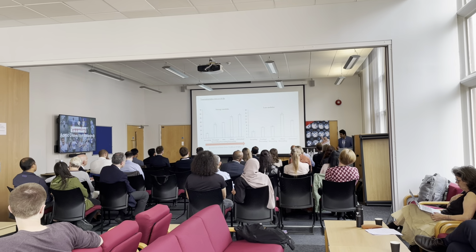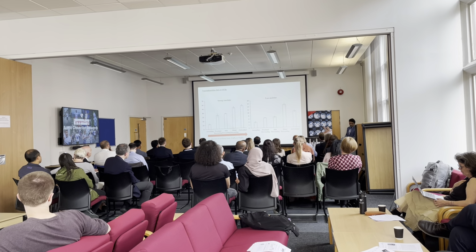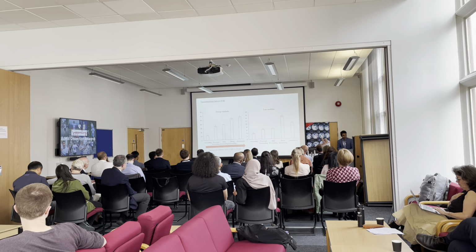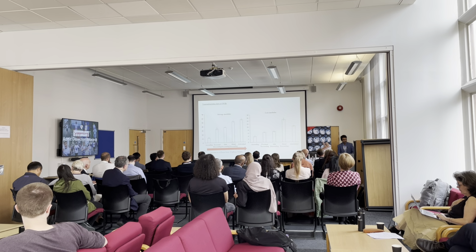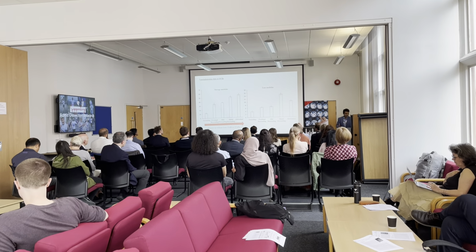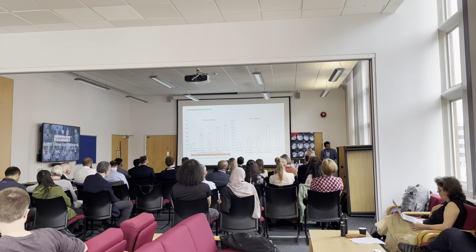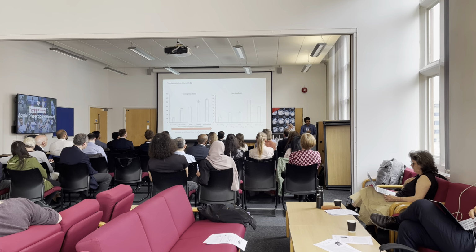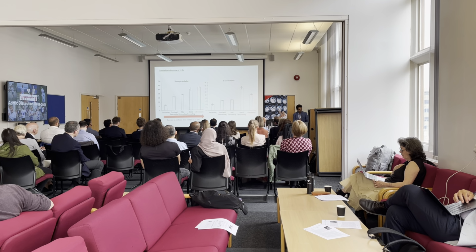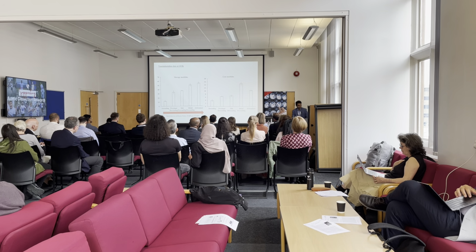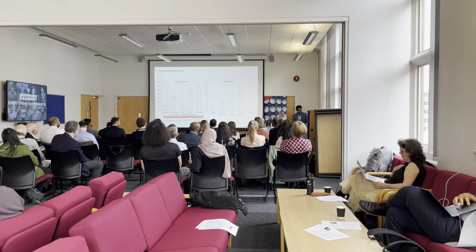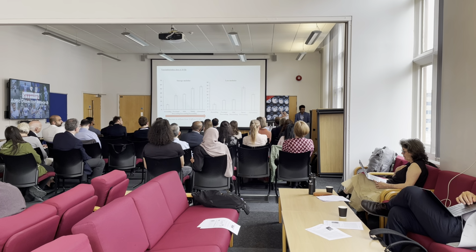The other interesting observation was that as we went from the ascending region of the aorta to the abdominal region of the aorta, we were able to see a very smooth increase in the storage modulus. So the stiffness, in terms of the storage modulus, increased from 10 kilopascals around the ascending region to approximately 55 kilopascals in the abdominal region.